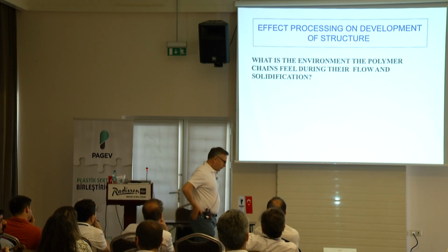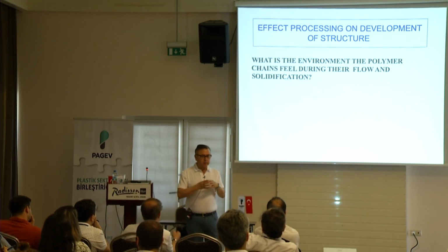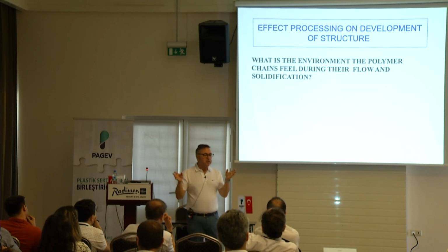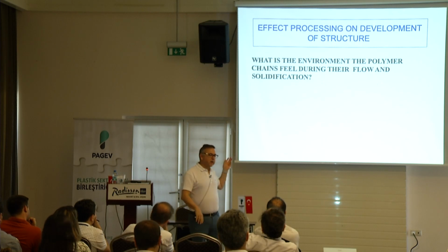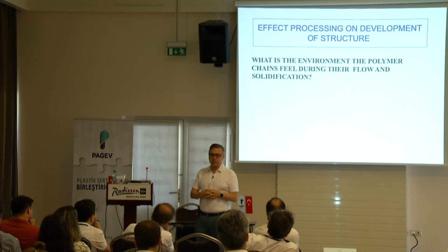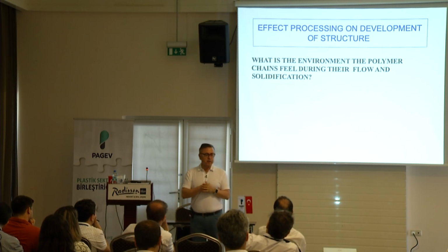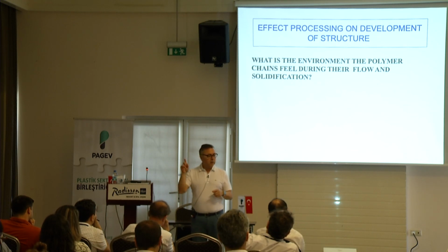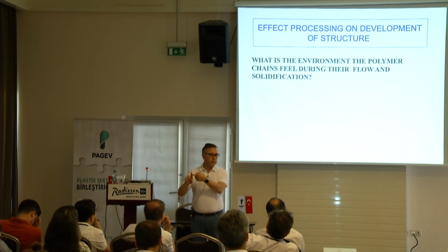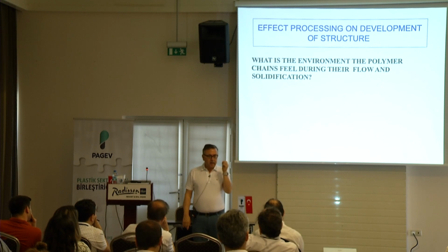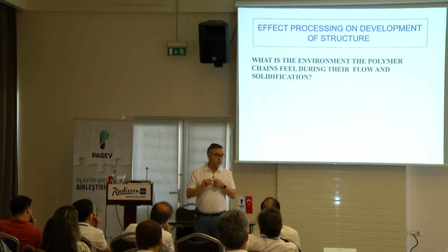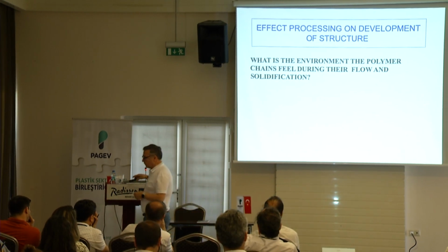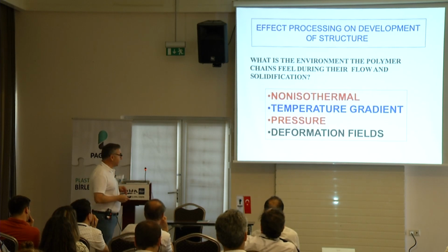So what I'm trying to prepare your minds for is what conditions I should consider to figure out how the material is going to behave in the process. Is it instantaneous conditions? Mold temperature, temperature of the melt inside the mold, or what has happened to it on the way to that point? Viscoelasticity says material has a memory, so what happens in the prehistory does influence the material. And this is the complexity in flow-induced crystallization, okay? And it's still keeping us busy for a very long time.